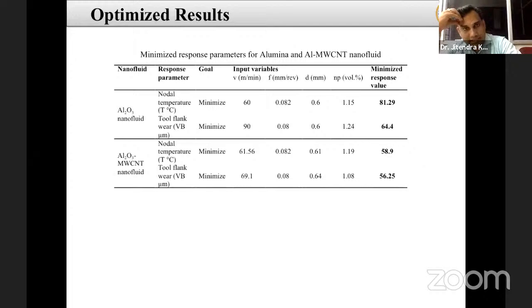So we took care of the optimum data, and from this RSM method we also obtained the optimum data. So for that particular data also, we performed the test, and we measured the output parameters of temperature and flank wear for both cases, alumina nano cutting fluid and alumina with MWCNT nano cutting fluid. So these are the optimum parameters whatever we have obtained through the software.